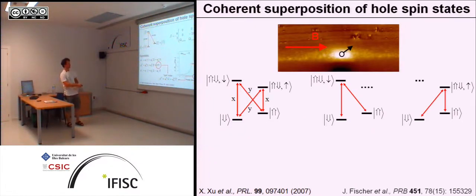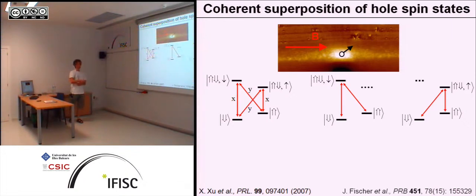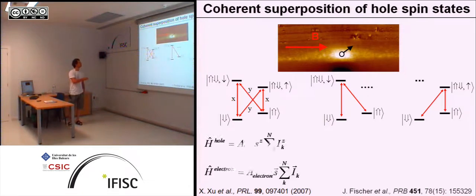Okay, and from that we can go straight to an experiment. How do we do this experiment? For this, we apply a magnetic field in XY direction, so perpendicular to the experiment before. Before it was in Z direction, now we apply it in XY direction. And that now changes the optical selection rules, and suddenly you have all these 4 transitions allowed. Before we only had 2 transitions, and now they're linearly X or linearly Y polarized. So that means you can now create 2 different lambda systems. This lambda system here coupling both hole spin states to the electron spin down state, or this lambda system coupling both hole spin states to the electron spin up state. But this is only an experimental necessity.